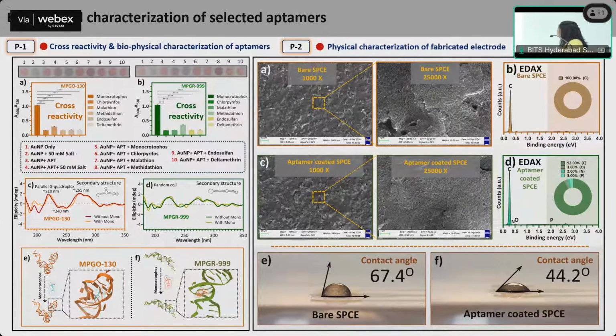Later, the cross-reactivity analysis was also carried out with a panel of pesticides, and specifically with monocrotophos, where we have observed that the aptamer is specifically binding with monocrotophos in both cases. CD analysis also gave us a clue that in case of MPGO-130, it is a G-quadruplex formation. However, in the case of MPGR-999, it is a random coil. In silico docking analysis also gave us the clue where exactly the aptamers are binding with the target. With this, we were sure that aptamers are binding with high affinity with the target. So let's go for the sensor fabrication.